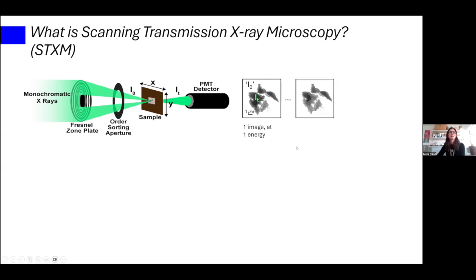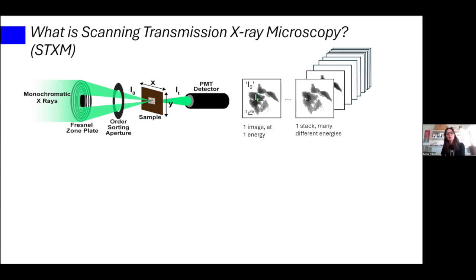Of course, what you can then do, because you're at a beamline, is change the energy slightly of the incoming light. Then usually, or hopefully, you will see the image change slightly, so that there are darker and less dark regions that switch between energies, because different things absorb light differently. And not only that, you can change it again and again, and build up an entire stack of energies, usually around a particular energy region that you have chosen with good reason.